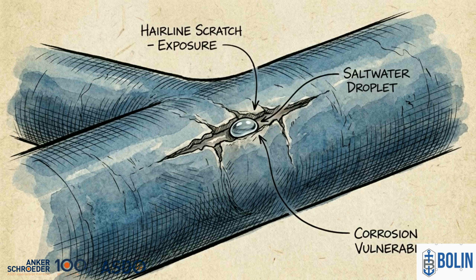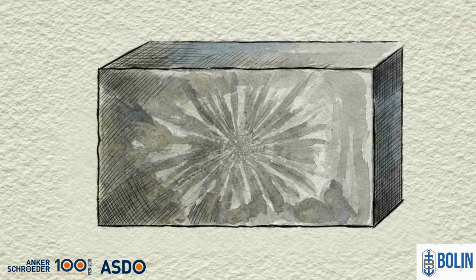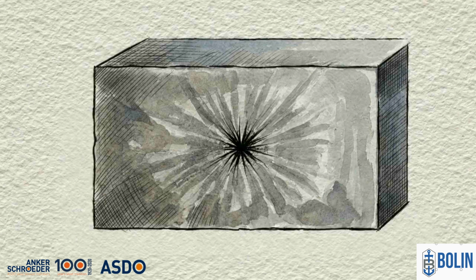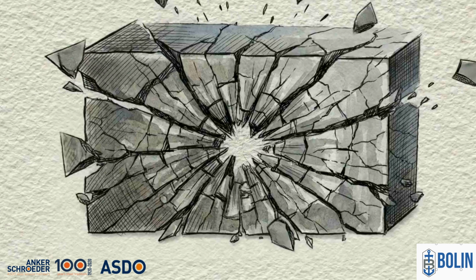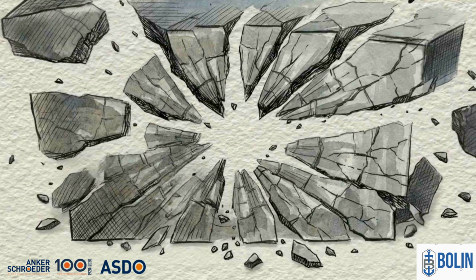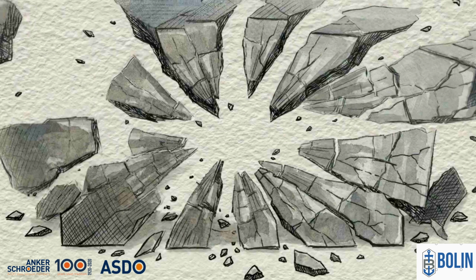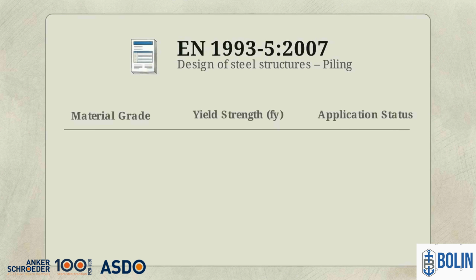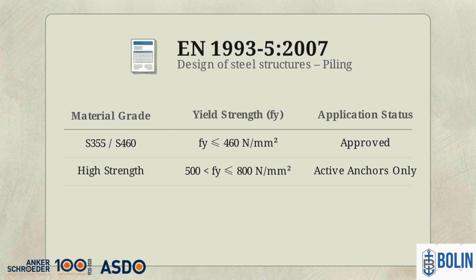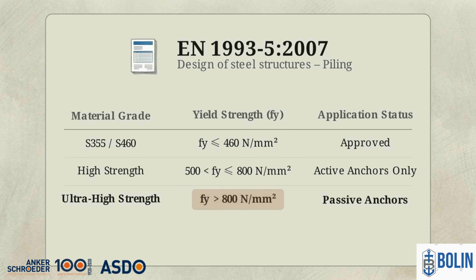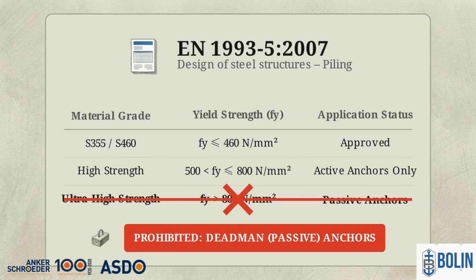But pushing marine steel to extreme strengths introduces an invisible threat. Under high tension and saltwater environments, ultra-high-strength steel becomes highly susceptible to hydrogen embrittlement. It can crack and shatter completely without warning. Because these failure modes are completely invisible until the moment of collapse, global design codes like EN 1993-5 actively prohibit this approach for Deadman anchors.